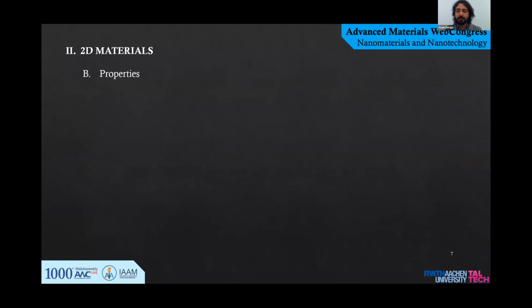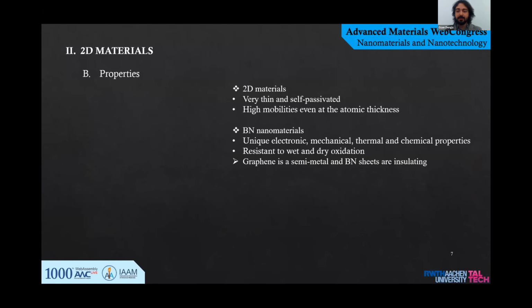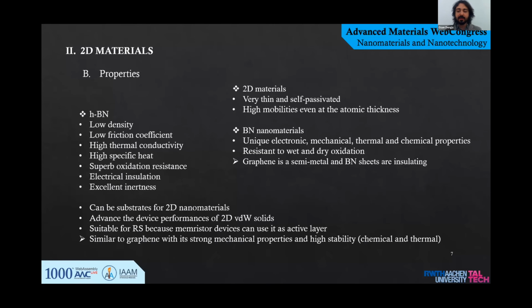About the properties of 2D materials, they are very thin and self-passivated, and they have high mobilities even at the atomic thickness limits. BN nanomaterials have even more unique properties. They are usually resistant to wet and dry oxidation, for example. And the major difference between BN and graphene is their electrical conductivity, since graphene is a semi-metal and BN sheets are insulating. More specifically, bulk HBN has these advanced properties.